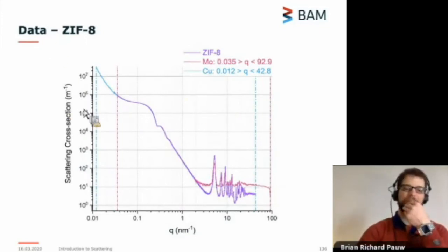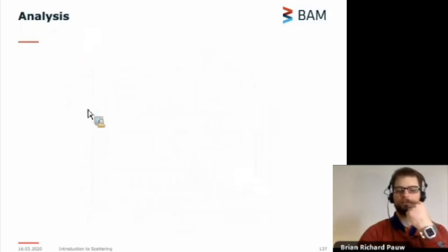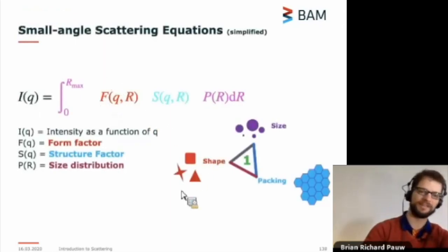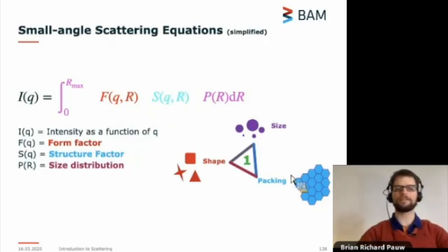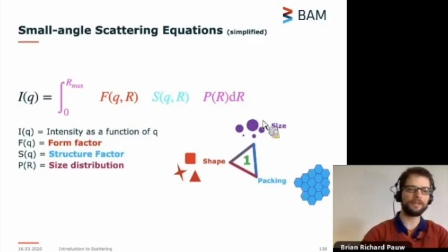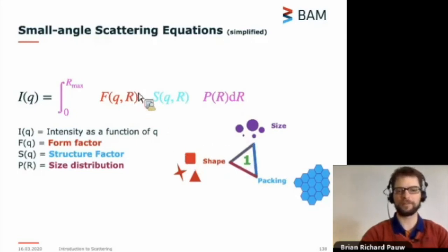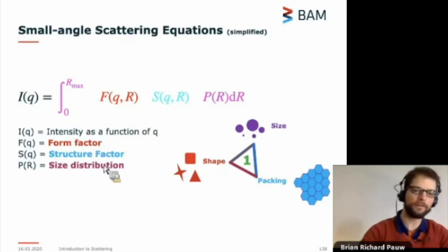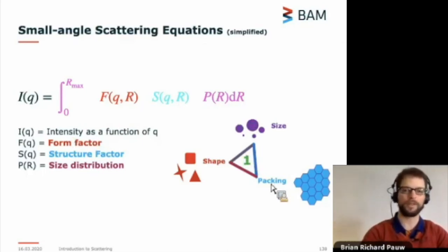All right. How would you go about analyzing one of these scattering patterns? If you look at scientific papers, you will often see equations like this. Now, this isn't 100% correct, but it is a relatively good way of describing the different elements that play a role. So we describe our intensity in three components. One is the form factor, which tells us something about the shape of our particles. The second one is a structure factor, which tells us something about the packing of our samples. And the third one is the size distribution, which is the information on the size distribution of these shapes. Both the form factor and the structure factor are dependent on the size. In principle, the structure factor is also dependent on the size distribution, which is why this is an approximation.